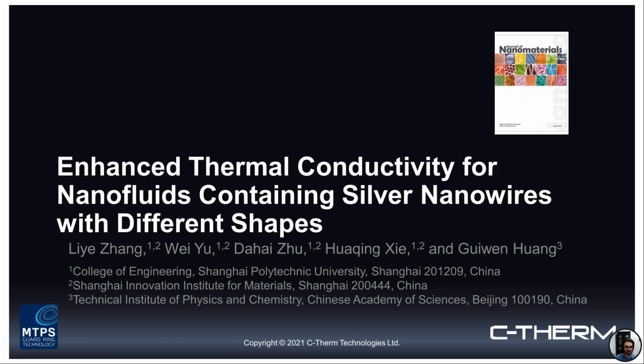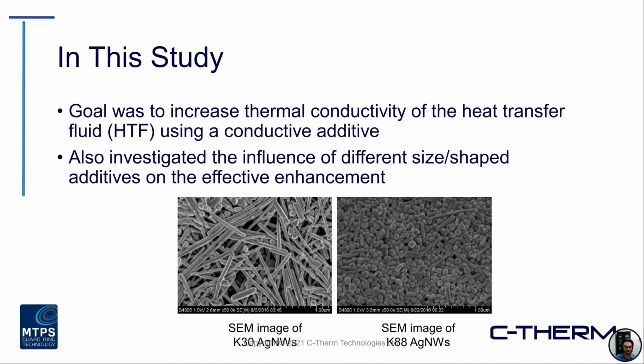So going into another example here of some work done in academia, enhanced thermal conductivity for nanofluids, and in this case looking at silver nanowires as the additive, but taking a look at how different shapes of your additive can come into play. This is some work coming out of China. Really, their goal was to increase the thermal conductivity of the HTF, the heat transfer fluid, using a conductive additive. But really making note here of the effect of the different shape of that additive. So it's the same material, silver nanowires, but in different size and shape formats, as you can see from the SEM images at the bottom there.